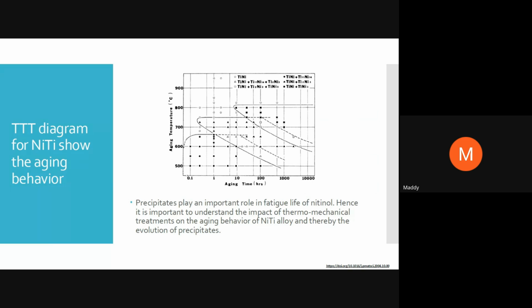One of the attributes that is important for your fatigue property is the precipitates. If you look at the NiTi system, there are different precipitates that can form, and there is a phase diagram that is going to come up in the upcoming slides. We'll talk a little bit more about that. But in the NiTi system, the nickel-rich side has a solvus that enables you to control the chemical composition as well as the properties through aging. And this particular example of the time temperature transformation diagram is for a specific composition of NiTi alloy.